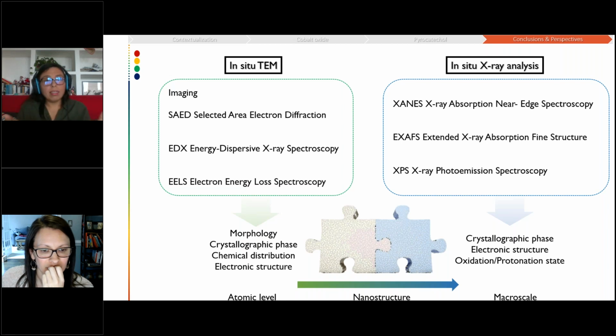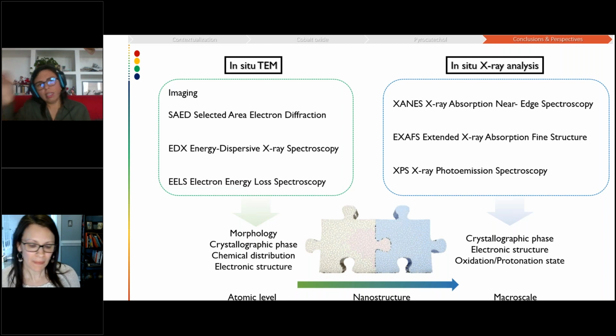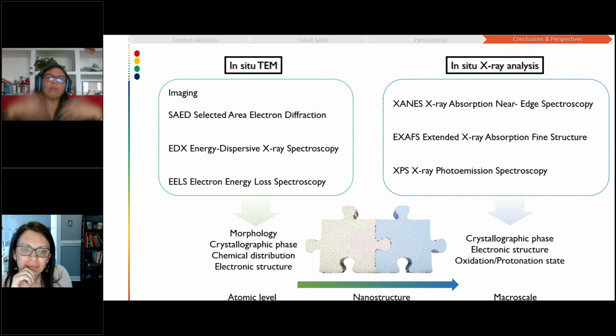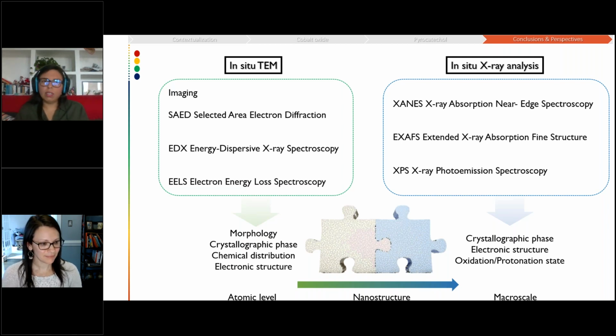electrochemical signature, for example. So I don't think that, if you don't go beyond a certain small thickness, it would impact the electrocatalytic activity too much. But you need to use more or less the same conditions that you would use in situ, for example saturating your electrolyte to make sure that with the outcoming flow of the electrolyte, you keep all the species that you need available for the electrocatalytic activity to take place. And second, finding a good scan rate for the cycling, because the depletion of species might happen faster than in a regular 3-electrode cell. If you go too fast, everything is going to go away. So those are things that need to be taken into account.